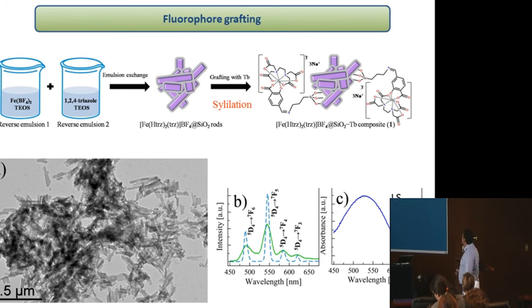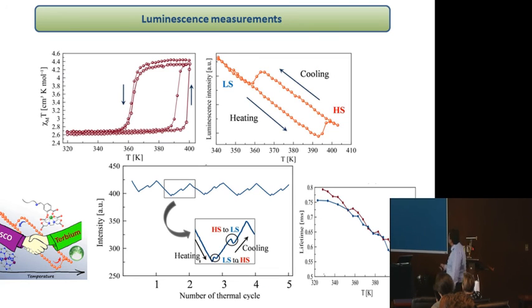Okay, just to finish, we also tried to graft different kinds of fluorophore, here for example terbium complexes. Again, we have good overlap between the two components. We obtain different shaped nanoparticles, modifying a little bit the experimental conditions. Here it's more rods than particles. And again, if you look at the fluorescence measurements, you have an important thermal variation for this fluorophore. But on the other hand, you have a very nice stability.